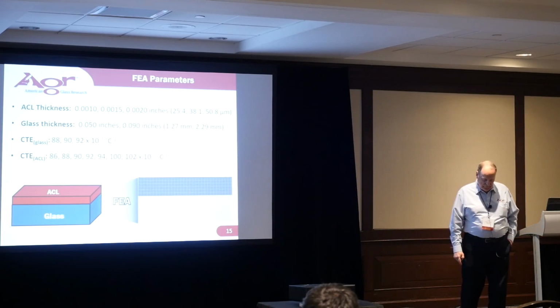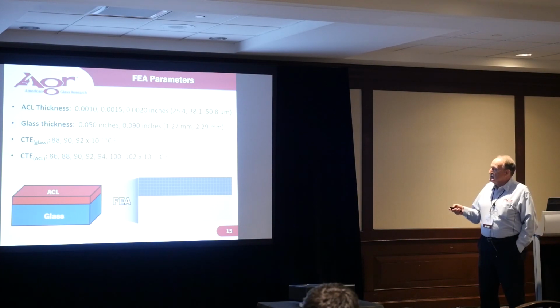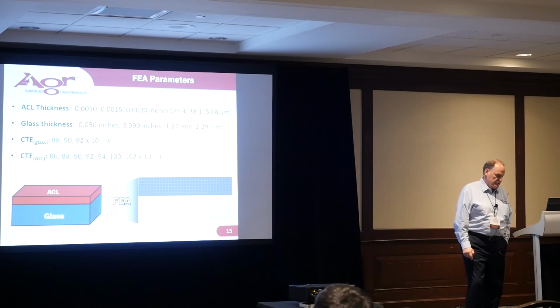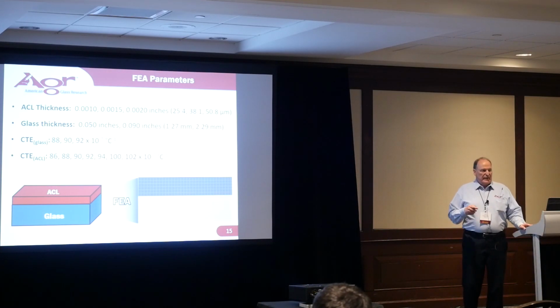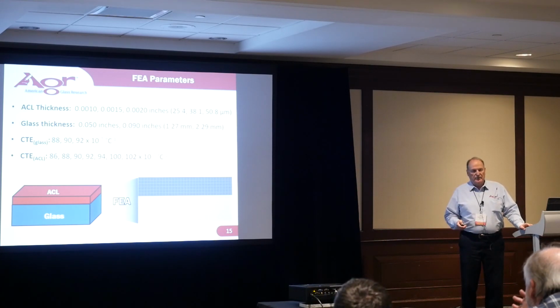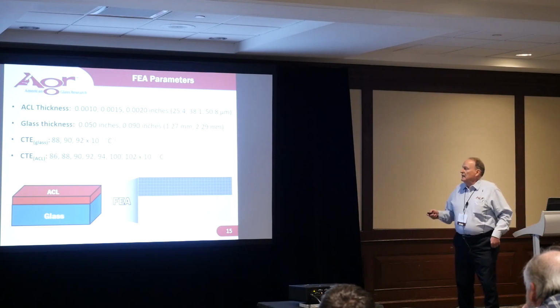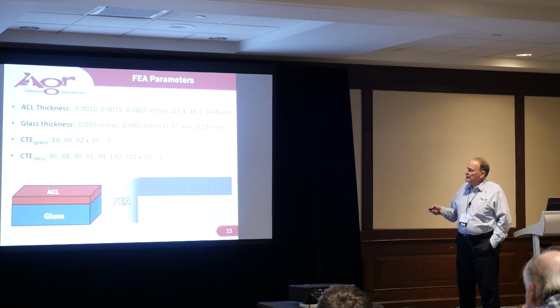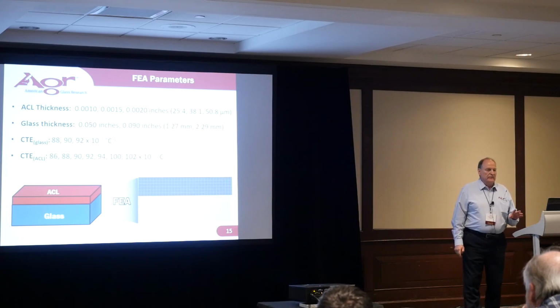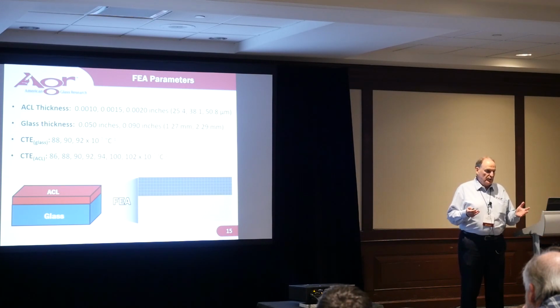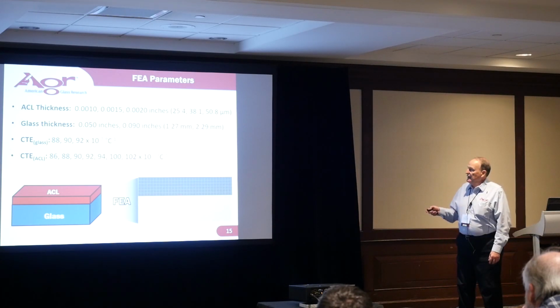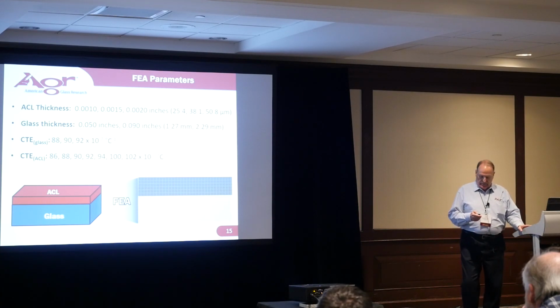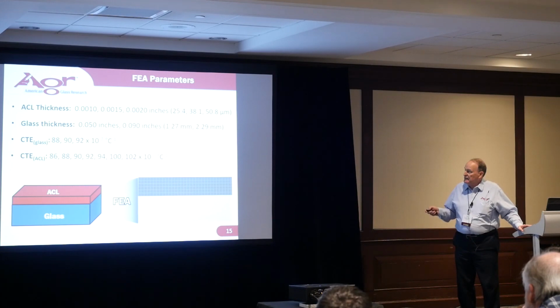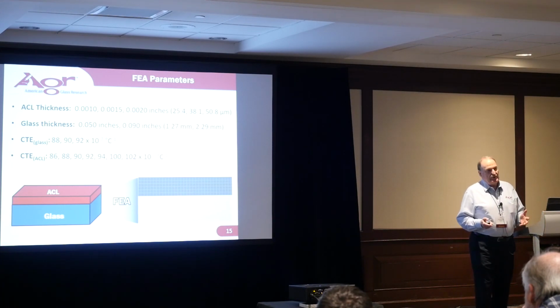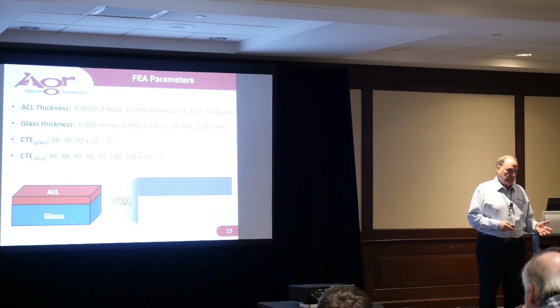Now, these are the parameters that we studied. We chose an ACL thickness of 1, 1.5, and 2 thousandths of an inch. These, through our experience, are about the right thicknesses for ACL materials applied to glass bottles. The glass thickness, we initially studied 0.09 inches, which is typical of the sidewall thickness of refillable bottles. If you remember, refillables were the ones that originally were decorated with these ceramic labels. Once we completed that analysis, we had some very interesting results, and we thought, let's go back, we'll repeat the analysis, but now we'll use a glass thickness of 0.05 inches, which is typical of the thickness of the sidewall of a non-refillable bottle, single trip bottle.